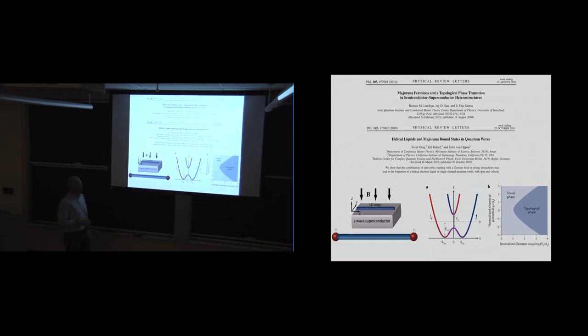And now the ingredients. What I can add is that these papers did something even nicer, both of them, which is they actually plugged in the numbers. They took materials like indium arsenide, indium antimonide, 3-5 semiconductors that had strong spin-orbit coupling, and said the gap that will emerge in a magnetic field in the presence of superconductivity will exceed the characteristic temperatures that you can easily achieve in the lab. Go for it. And we did. But it took 10 years of turning this into a concrete, experimentally realizable proposal before we went to work.